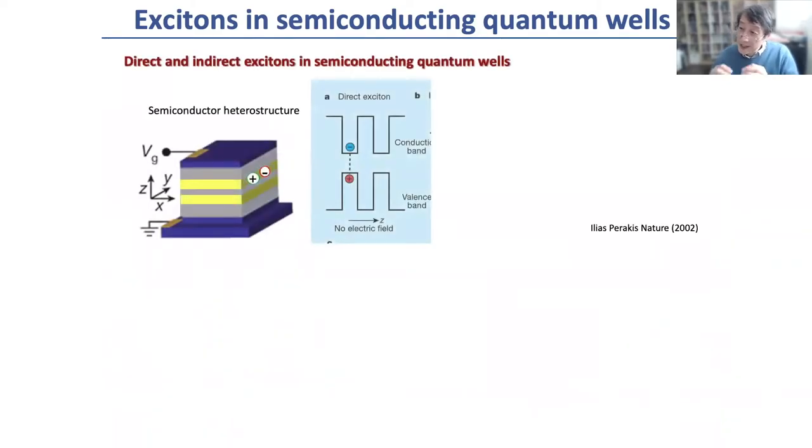However, is it possible to realize excitons that live long enough without the light or the coherence drive? There's yet a different approach we can learn from semiconductor heterostructures. Basically, can I make this exciton live very long? The way is that we can separate the electron and hole, not leaving them in the same place, such that their overlap becomes small, so the exciton lives long. In this example, you can make a double quantum well, right? And create the exciton in one of the quantum wells.